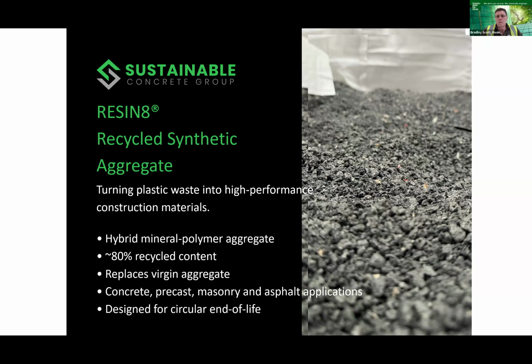Yeah, we have scientific reports on the leachate and the microplastic scenario. So when you're recycling this as an aggregate going forward, you don't have restrictions, as you would if you had plastic in concrete. You can't put that near waterways and other such things because it's a contaminated aggregate. This is not a contaminated aggregate. Because we've cut those pathways off in the plastic to those two things, there's no contamination going forward. It's just an aggregate. Thanks, Brad. And next slide, please, Toy.